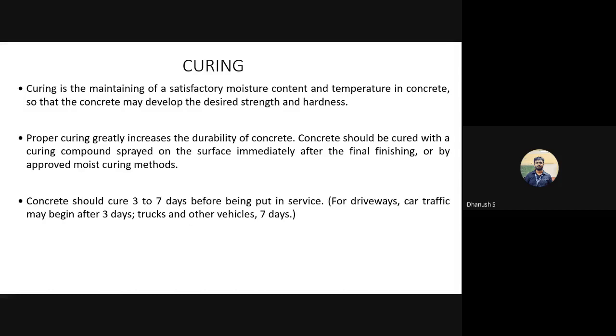Okay, some contractors, to be on the safer side, do it for at least 14 days. So 7 is minimum, 14 is good enough. Anything beyond 14, if you do, no harm. It will obviously add to the strength of the structure. Even if you don't do it, the loss of strength is not going to be that much. Okay, because at the end of 7 days, the concrete has gained about 67% strength. Okay, so anything beyond that, the curve sort of flattens. The rate of strength gain actually smoothens. So the first 7 days is very, very important. Keep this in mind. Next.